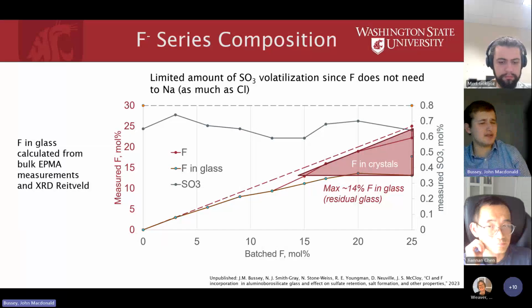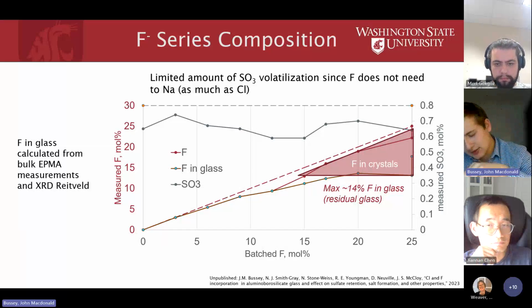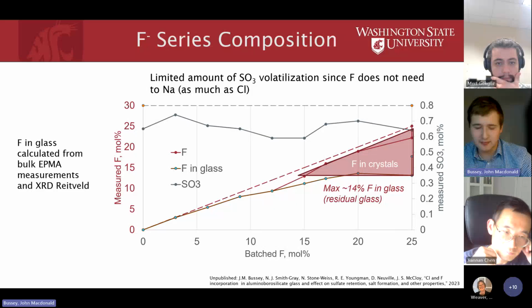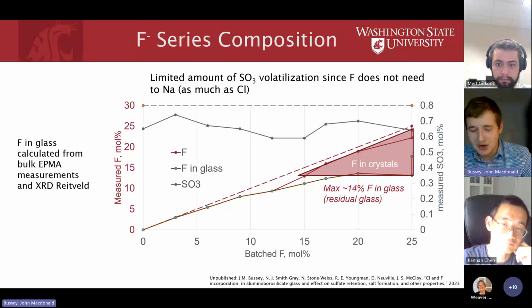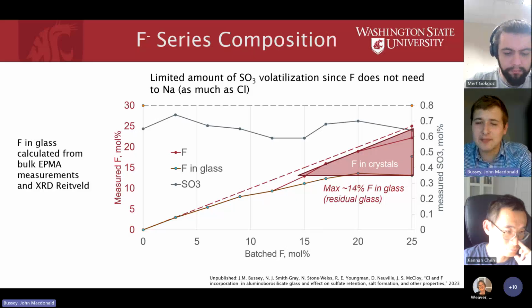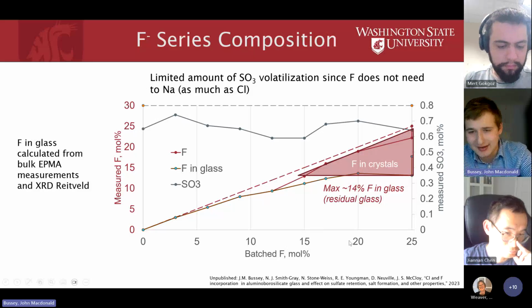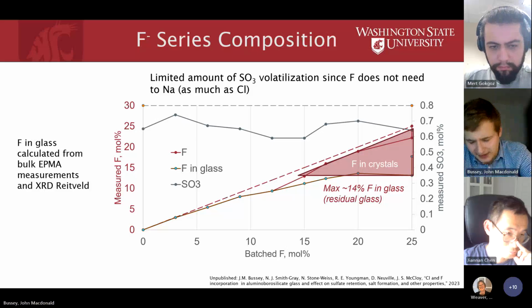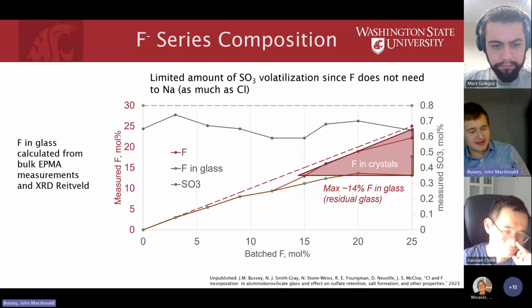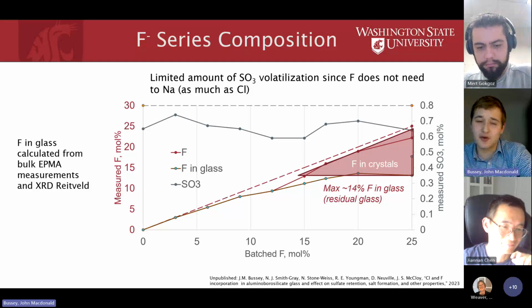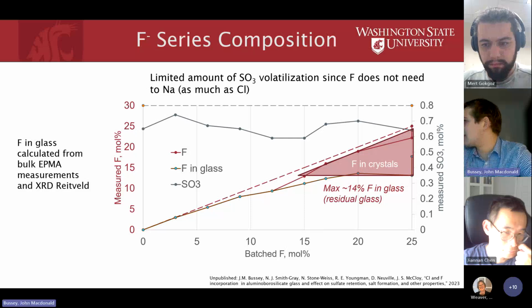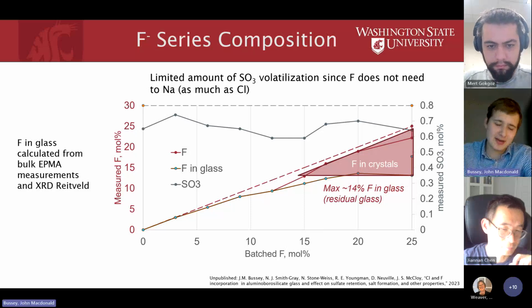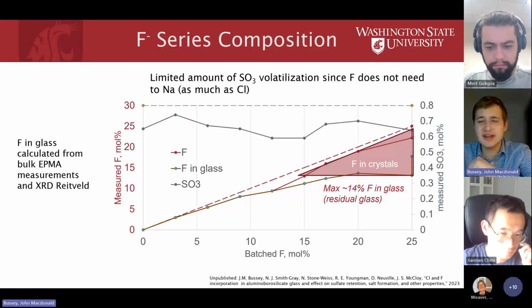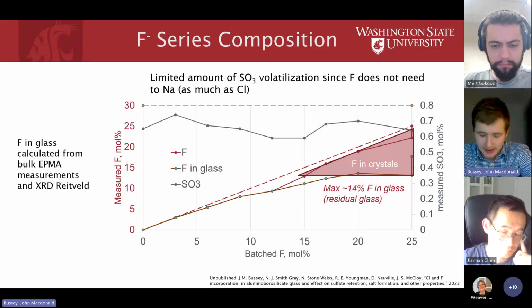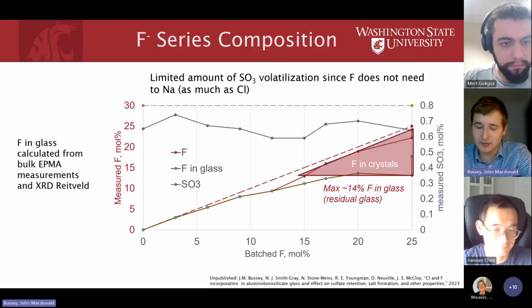But we devised a method using the fluorine measured that includes crystals and glass, and the known weight fraction of crystals from Rietveld refinement of our X-ray diffraction, to estimate what the composition change looked like. We saw that the fluorine appeared to plateau at around 14% fluorine in the glass, with the rest going into crystal. The other thing to note is that the sodium and sodium aluminate phases form only after calcium is entirely depleted. That's quite interesting. We know from a collaborator's molecular dynamics simulations that fluorine is most highly desired to bond with calcium.